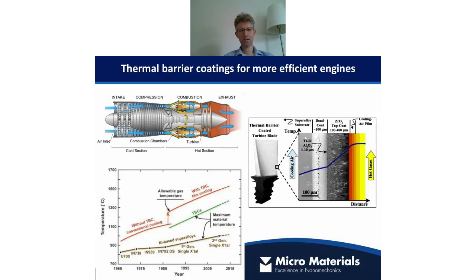That's the real challenge. In a jet engine, a thermal barrier coating is the key system that enables you to operate the jet engine above the melting temperature of the nickel-based superalloy, which is the turbine blade material. It's quite unusual, if you haven't thought about it, that by a combination of this thermal barrier system and advanced cooling, every time you get in an aeroplane, I know we're not doing a lot at the moment, the temperatures in that engine are higher than the melting temperature of the alloys in the engine. And yet it's still working very nicely because of this very clever composite coating system that allows us to drop several hundred or 100 or so degrees across this zirconia top coat.